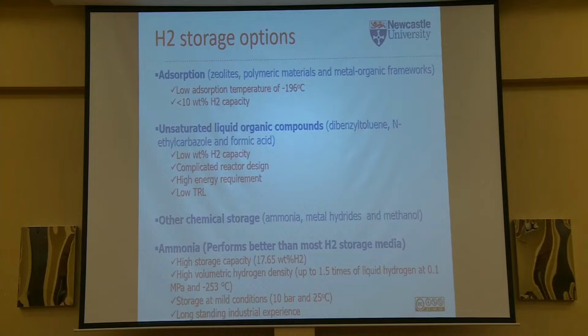Ammonia is very popular for this application because ammonia has high hydrogen storage capacity. Of course, it also has high volumetric hydrogen density, which is around 1.5 times when you compare it to hydrogen itself. We can also do that at relatively milder conditions. So we can transport ammonia at, say, pressures as low as 10 bar. And then lastly, there is a lot of experience with transporting ammonia in the industry.